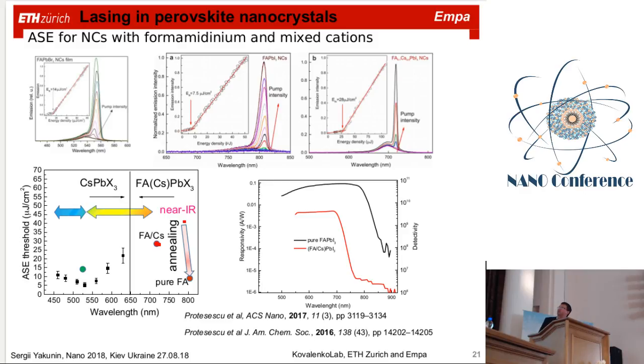So actually, as you remember from the previous slide, we have certain problems: we have a very high ASE threshold, and we did not reach the near infrared range. We had really higher thresholds in the red range, but due to the ability of those nanocrystals to merge together under thermal treatment, they start to merge in the thin film, and it also improves exciton coupling in such a film. And then we have a really big drop in optical gain threshold. So those films show a really nice effect for optical gain.